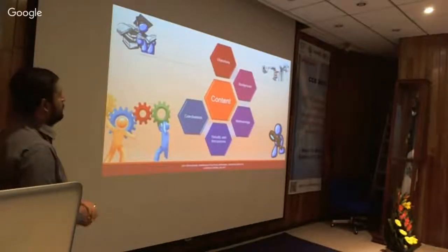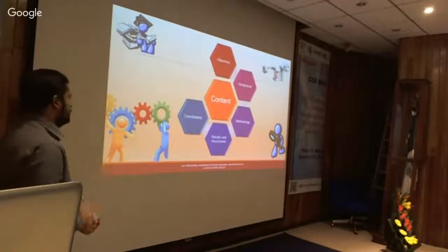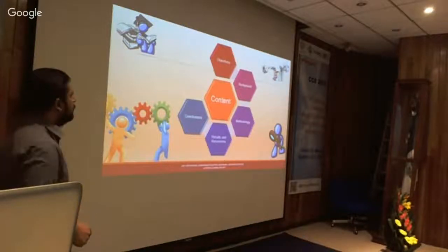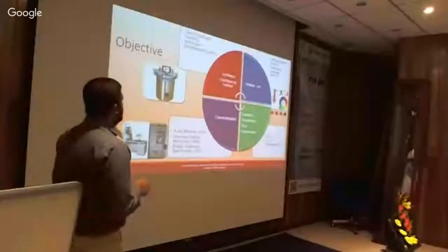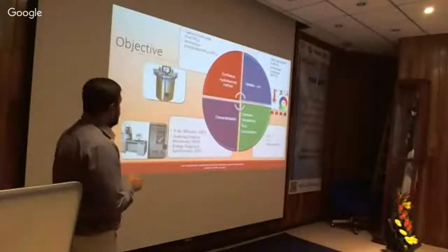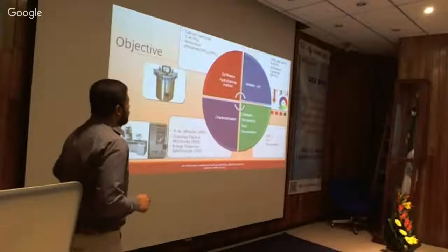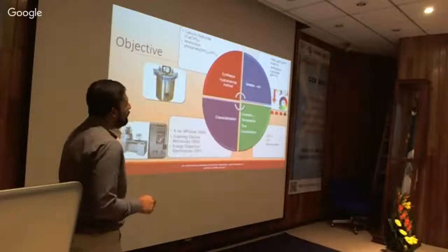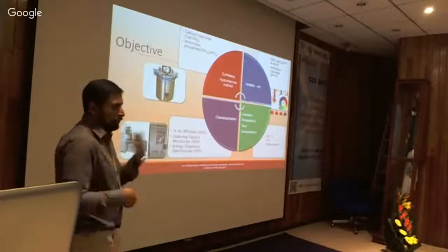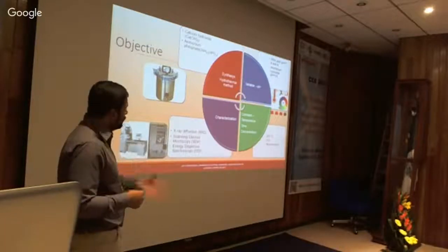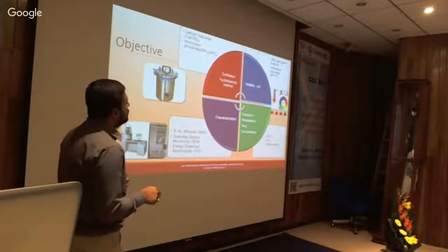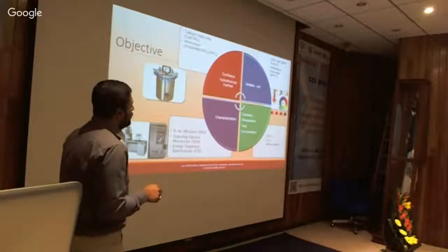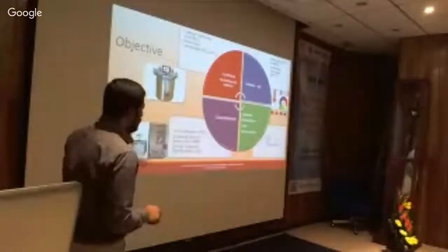So I will explain primarily the objectives, the background, methodology, results and conclusion. The main objective of this work, as the title says, is to synthesize hydroxyapatite using calcium hydroxide and ammonium phosphate as precursors. Here we study the effect of the pH on the structural properties. We decrease the pH using nitric acid, and we increase it by using ammonium hydroxide. And we left the remaining parameters constant in this part of the work.